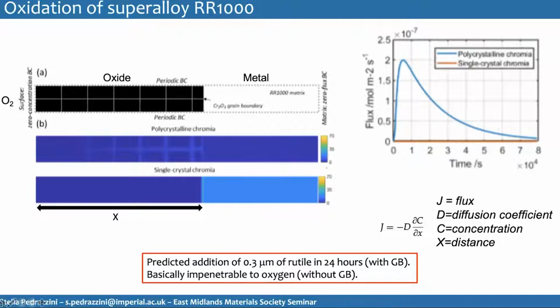So if we have the oxide on the surface here on the left, the metal on the right, and the grain boundaries, if there is titanium diffusing outwards at the grain boundaries, the prediction would be that this would cause the addition of 0.3 microns of rutile in 24 hours, which is more or less as accurate as we observed. But without the grain boundaries, just looking at the number of extra vacancies and how much that would speed up diffusion, the conclusion was that this is basically impenetrable to more oxygen. So the diffusion would be that slow.